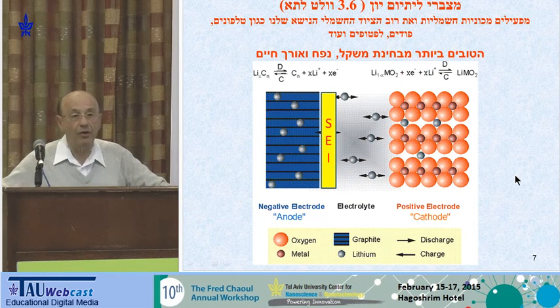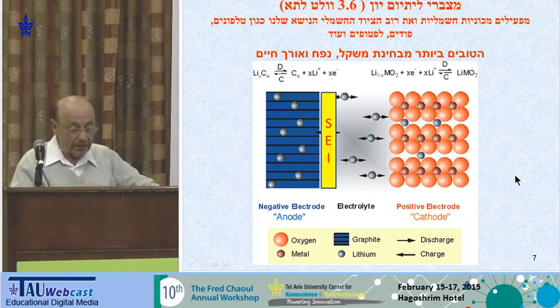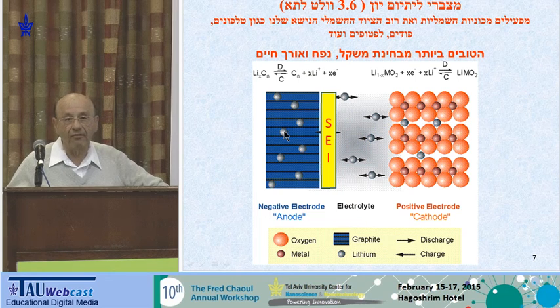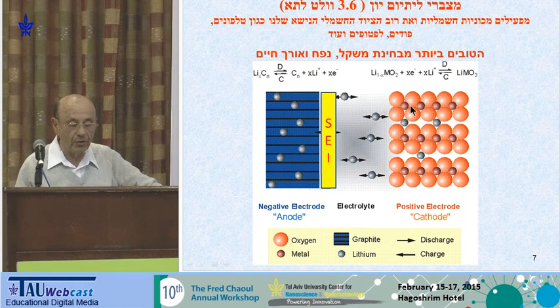So some information on how a lithium-ion battery works. It has an anode. Today the anode is made of graphite, and we insert or intercalate lithium cations into the graphite during charge, and they leave into the solution during discharge. And we have some lithium metal oxide cathode, that takes the lithium cations into it, and electrons, during discharge, electrons going this way, and during charge going this way. On top of the graphite anode or any anode, there is what we call the solid electrolyte interface, which is a nano-size solid electrolyte, very important.